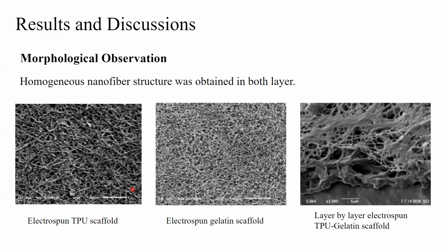Let's continue with results and discussion part. For the electrospun scaffolds, morphological observation was performed by using scanning electron microscopy, and as a result, homogeneous nanofiber structure was obtained in both layers. In the third picture, we can see the morphology of the double-layer electrospun fibers.